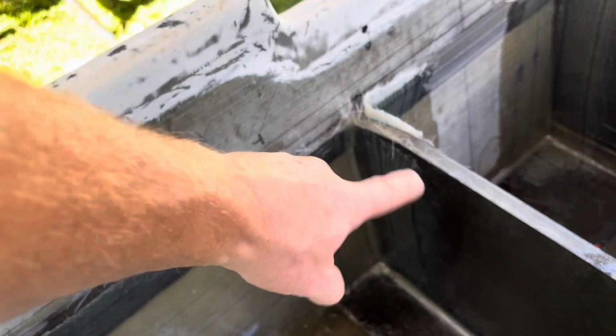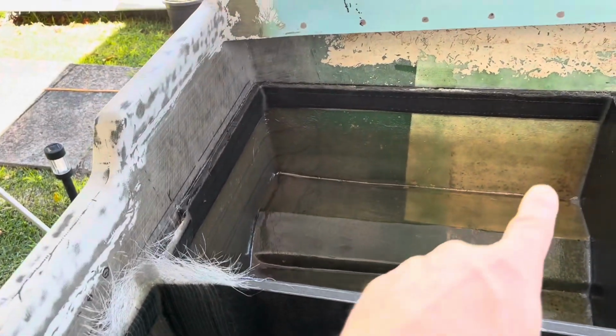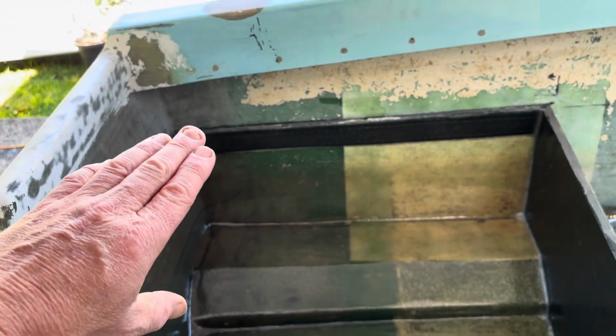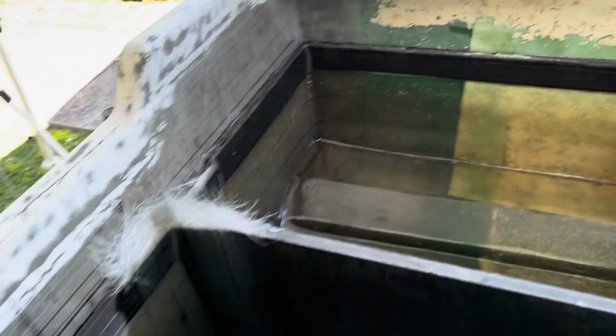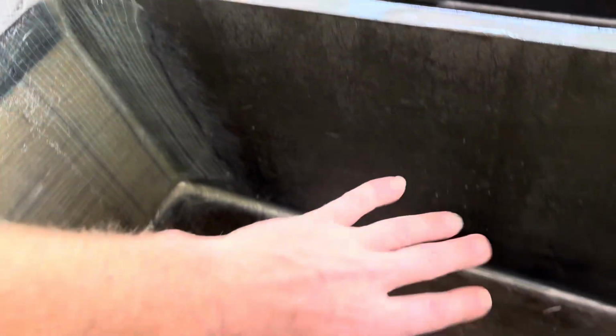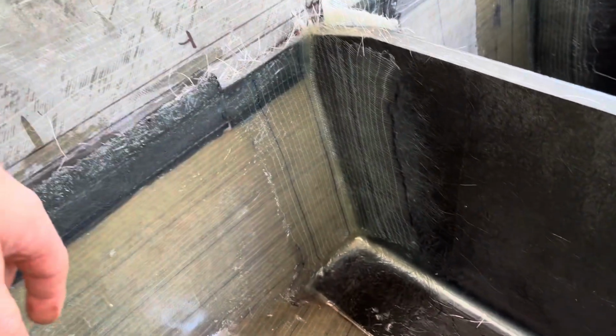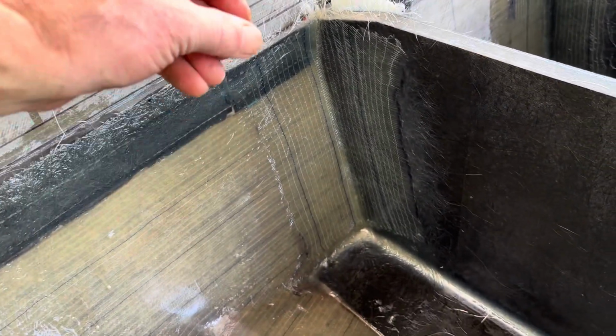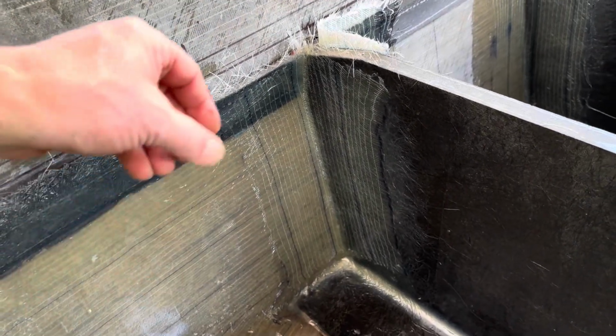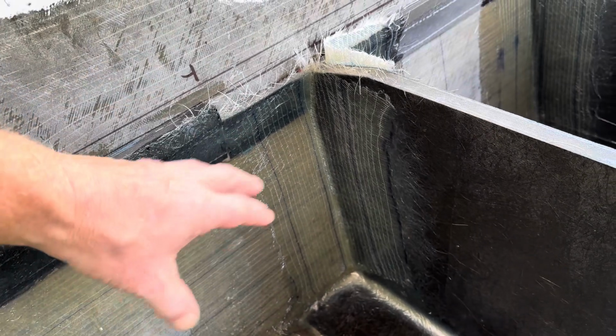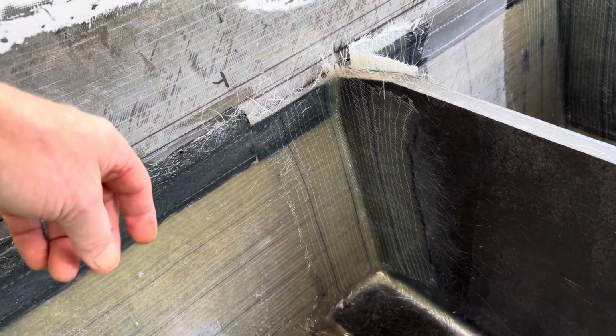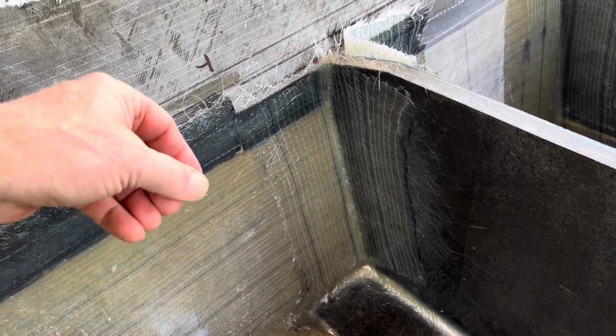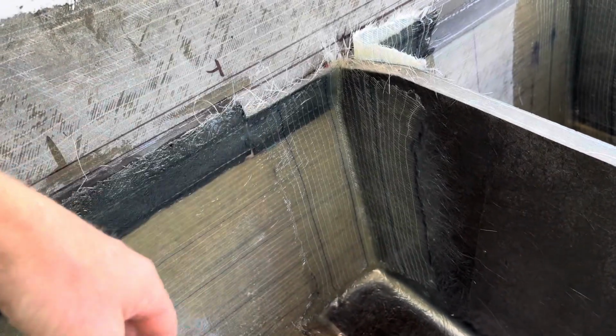So I've gone ahead and laminated all of my tabbing in, including some chop strand mat from the little rail there down to the hull. The reason I've done this tabbing before I've gone ahead and done chop strand over all of this thermalite is because you've got to watch the thickness of your laminations as you laminate, because if it's too thick, it can start going off too quickly because of the chemical reaction, and it can ruin the resin and also the strength of the finished product. So just be careful how thick you laminate. You wouldn't go ahead and put, you know, 5 layers of 600 gram material, because it would end up burning the resin.